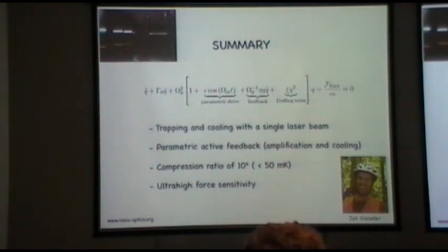Thank you. Another question. What about the material of this nanoparticle? This is fused silica. It was purposely chosen to be fused silica because, if I talk about temperature, what I refer to is the center of mass temperature. But the internal temperature of the particle can be very high. In fact, the internal temperature is just given by the balance of absorption from the laser and black body radiation. We can't measure that, but of course, if the intrinsic absorption by the particle is too high, you will melt the particle. Fused silica has a very low absorption coefficient, and that's why we use it.